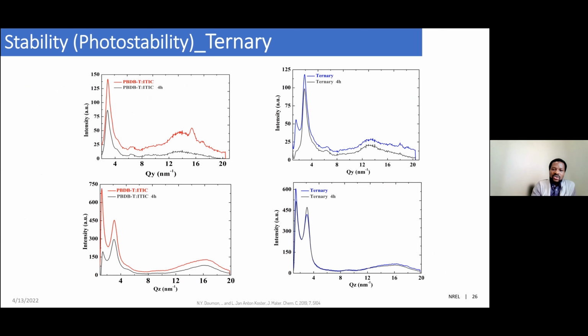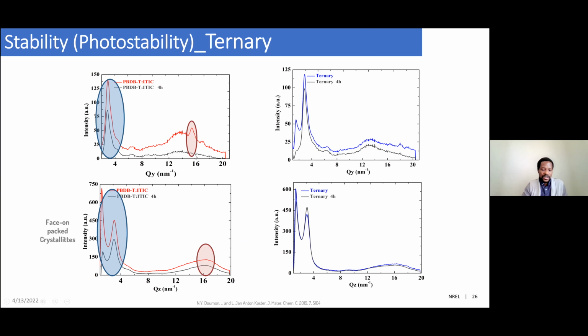So we look at our collaborators who can do GIWAXS measurement for us. And here, when you look at the edge-on crystallite, we can see that the peak degraded rapidly. And when you look at the in-plane, the 010 in-plane peak around 15.4, this disappears rapidly after a few hours. And that shows that the similar observation has been made for the face-on crystallite, which also degrade rapidly over time for the ITIC devices, which means that this system loses its crystallinity, and the molecular packing is being disturbed.